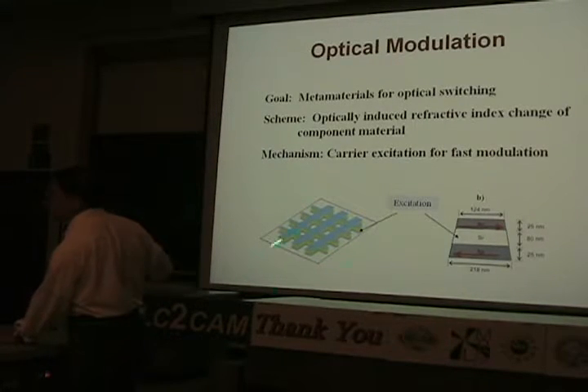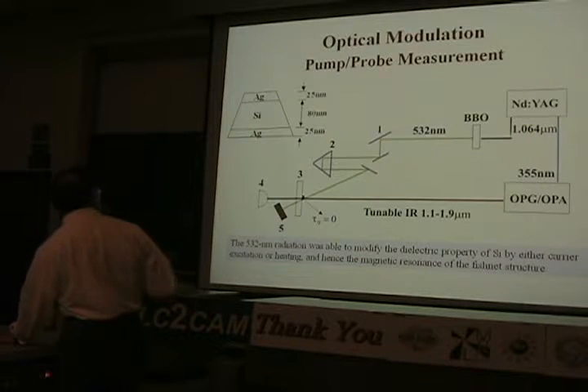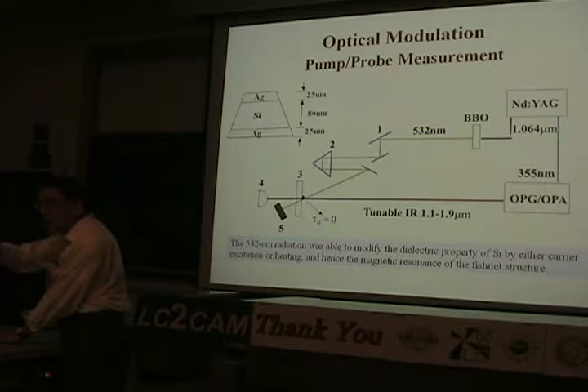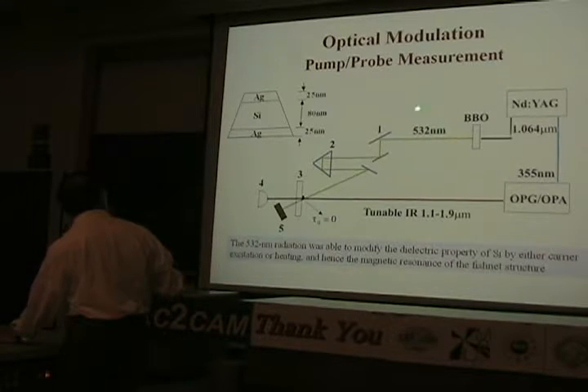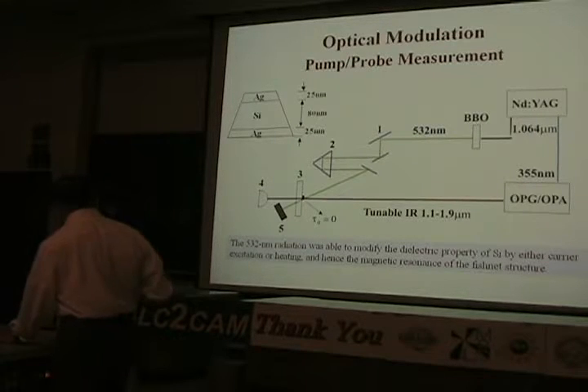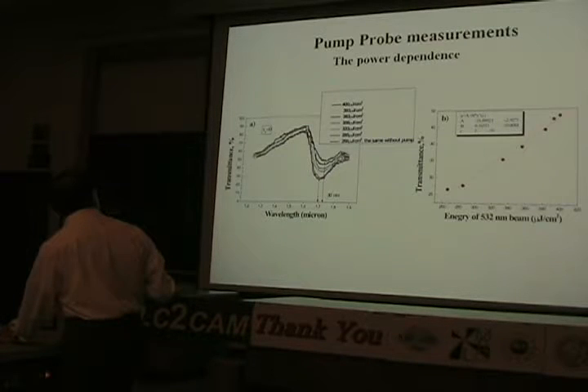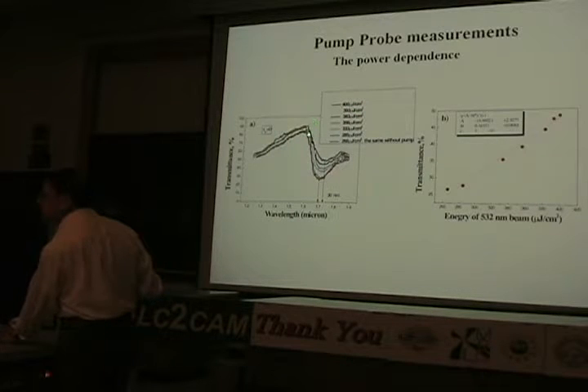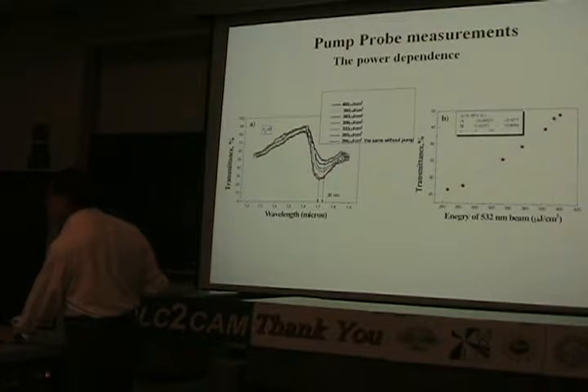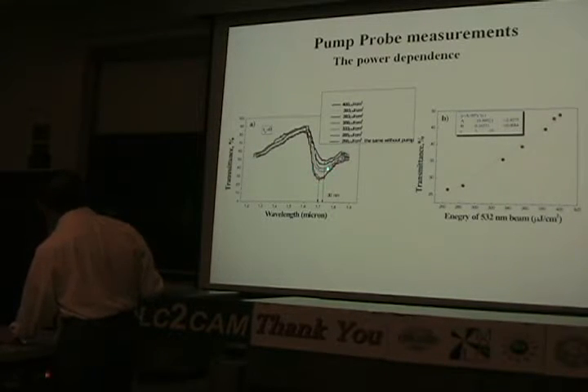So with this structure, what we do, as you can imagine, is we just use a pump beam exciting this metamaterial, and then a probe beam to probe the change of the refractive index. So that's the pump-probe experiment. I think everyone knows it well. So we use this tunable infrared as a probe to probe the resonance region. And the pump is this 532 nanometer beam. It's a picosecond pulse system. And with that, you can see that for different pump fluences on the sample, this transmission curve changes. Okay. And also the resonant frequency, or the dip frequency, changes.